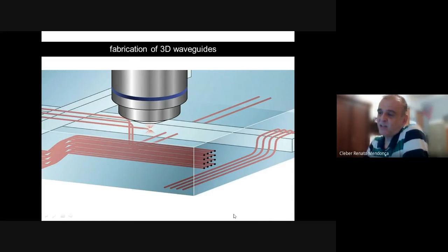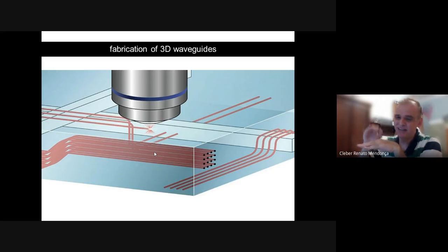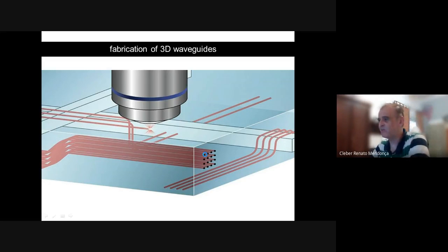So what can we do with that? We can focus the laser beam inside a given material, and by controlling the nonlinear interaction, we can modify that material to produce three-dimensional optical circuits, for instance, right? So as I'm showing here, we can fabricate waveguides, which are, let's call them, like optical fibers, which are actually immersed inside, in the bulk of a given material. So by controlling the movement here, of course, by controlling the intensity and the number of pulses and lots of things, we can actually fabricate waveguides.